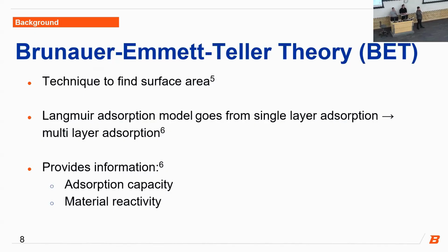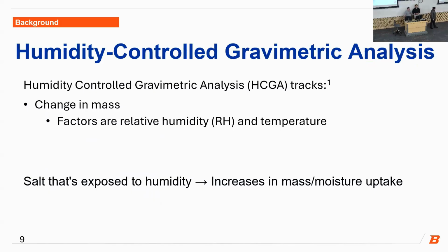So in order to understand the hygroscopicity, knowing a salt's surface area is important. The Brunauer-Emmett-Teller method, or BET, is an analytical technique used to find the specific surface area of solid materials. The method is based on physical adsorption of gas molecules onto a solid surface, and it extends the Langmuir adsorption model from a single layer to multi-layer adsorption. The BET method also provides critical information about surface area, which strongly influences the adsorption capacity and material reactivity. And then the humidity control gravimetric analysis, or the HCGA, tracks change in mass due to factors of relative humidity and temperature. So salt that's exposed to humidity increases in mass and moisture uptake. And I'll turn the time over to Jacob.